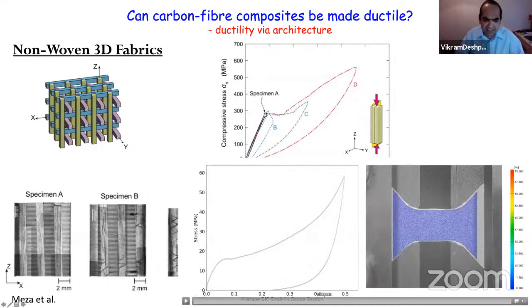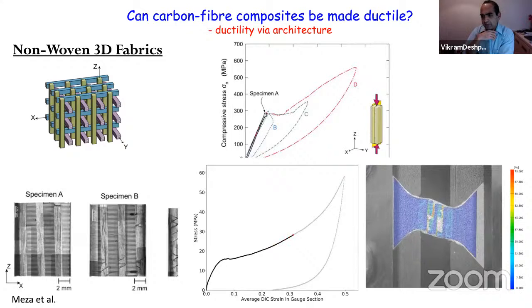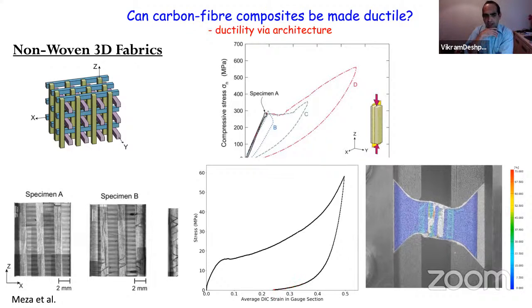Now, this translates into shear as well. This composite is extremely ductile even under shear loading, and this is the experiment to show that it's at 50% strain and it's still not undergone catastrophic failure. Although the reason for this ductility in shear is very different. Basically you've got fibers in all directions, and so you don't get these kind of delamination failure events that occur in typical, at least 2-dimensional, composites.